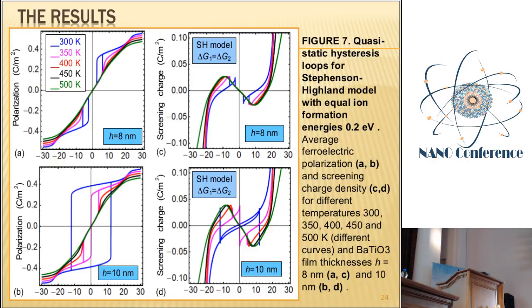For a thicker film, 10 nanometers, the limit of true nanomaterials, we have a single hysteresis loop at low temperature with a high enough coercive bias for applications, and this loop becomes a double one with temperature increase and finally disappears at elevated temperature of a high hundred of Kelvin. This situation is for equal formation energies.